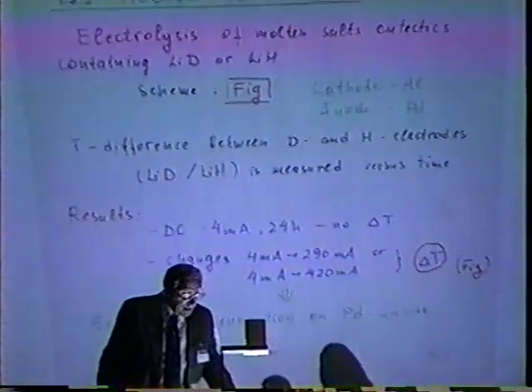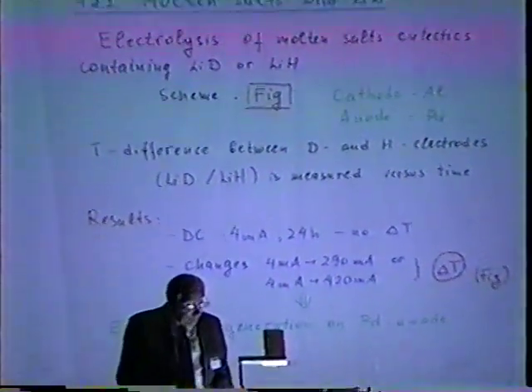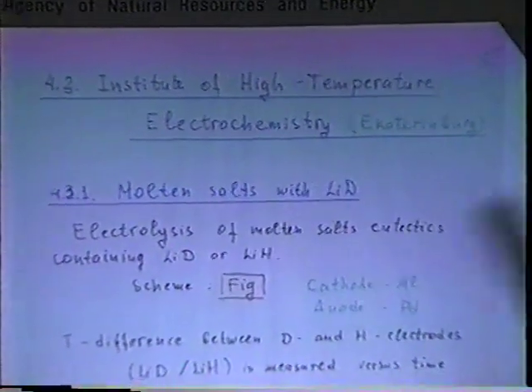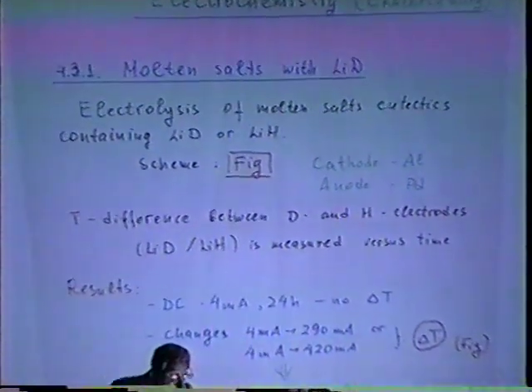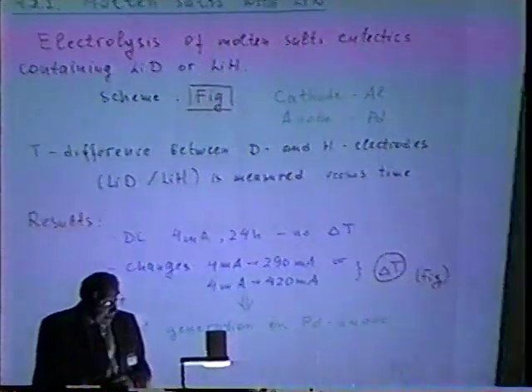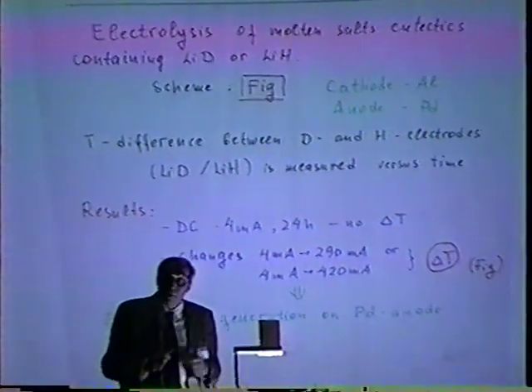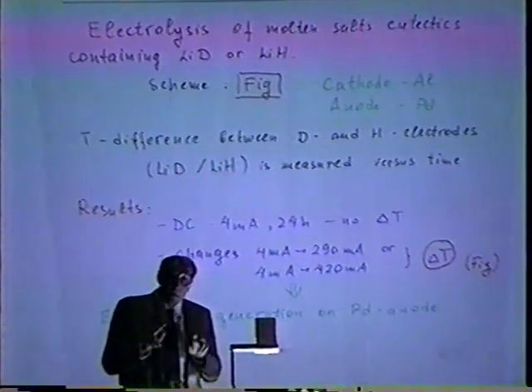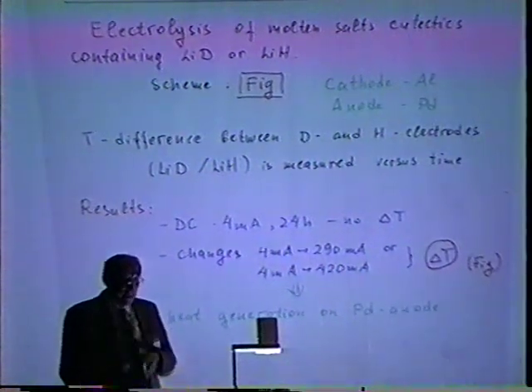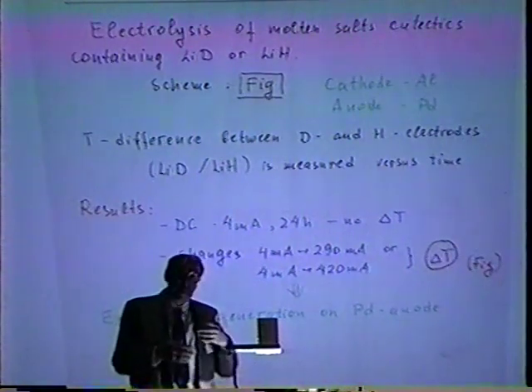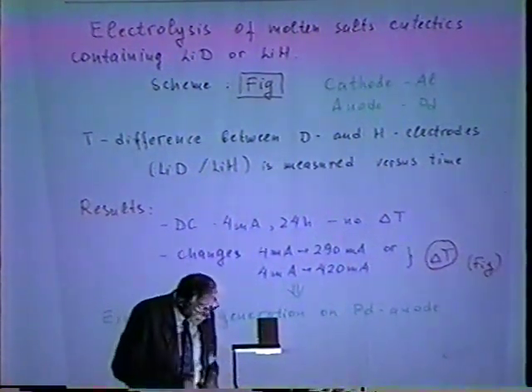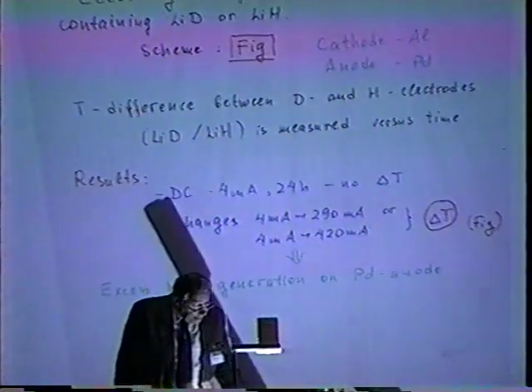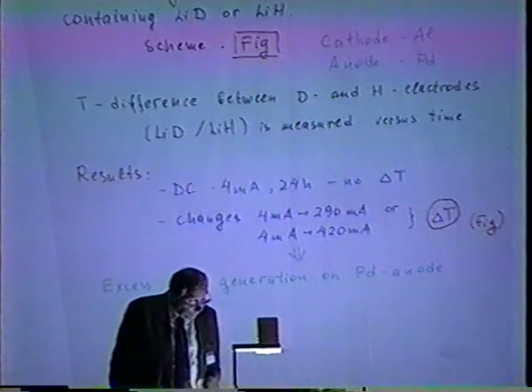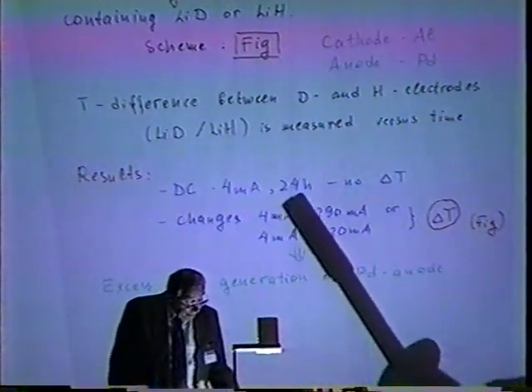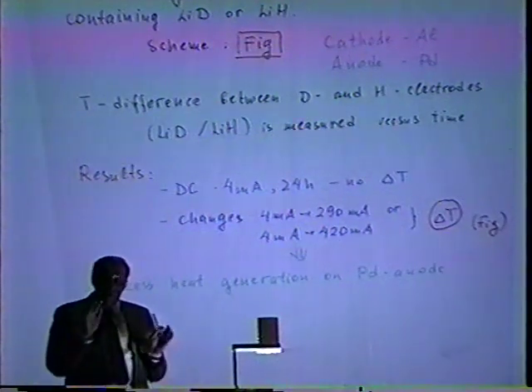In the same institute, another work was presented, this time with molten salt electrolysis with lithium hydride. So it's very close to Leon's ideas. However, they use a little bit, maybe more interesting, procedure. They use in parallel two cells, one with deuteride materials and another with hydride materials, and they can measure directly the difference between these two cases. And their result: if they use direct current for electrolysis, with a current density of about 4 milliamps, after 24 hours there was no difference between these two cells.